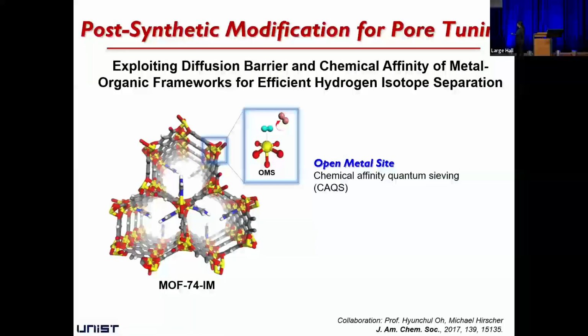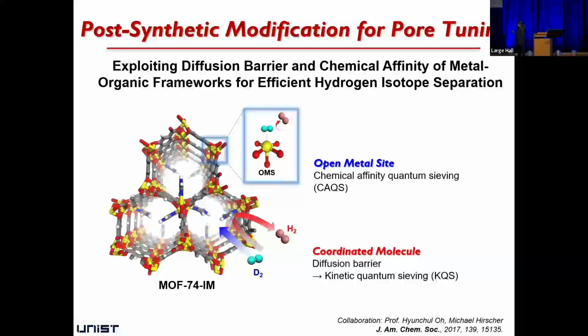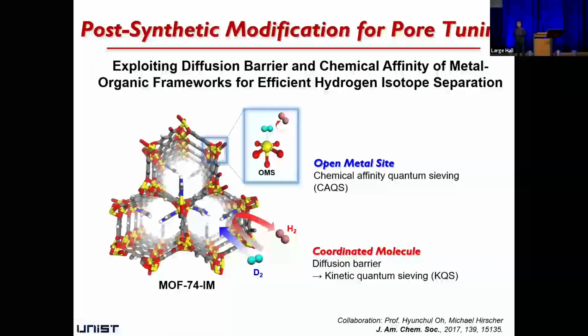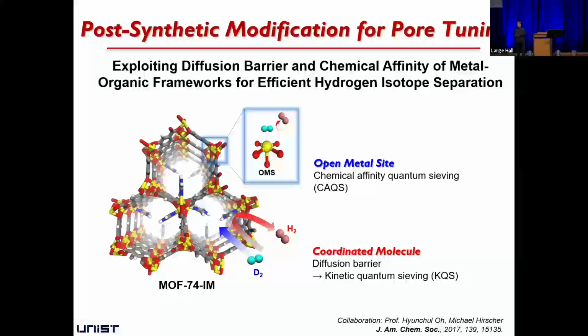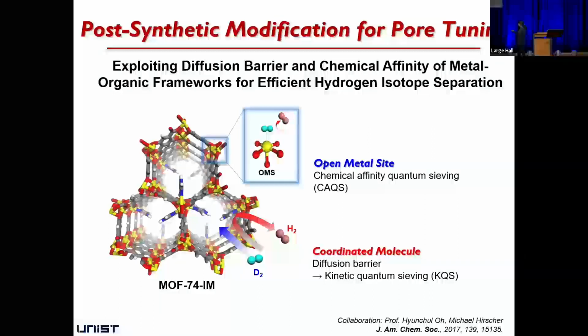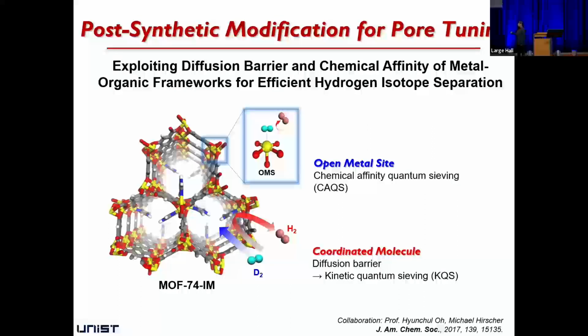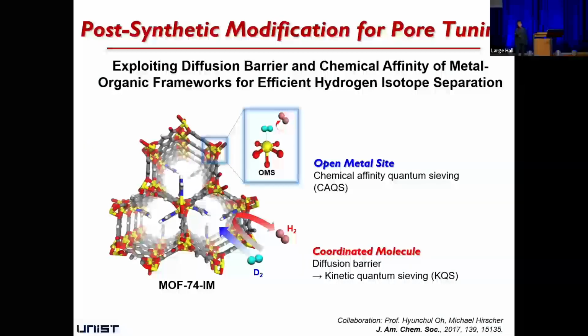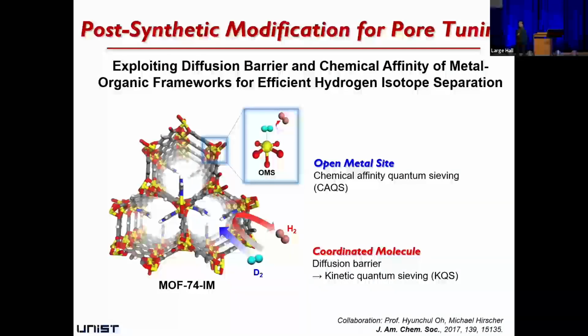So we choose the MOF-74. As you know, MOF-74 has a high density of open metal sites and very strong sites. So we can expect the chemical affinity quantum sieving effect from the open metal site, but MOF-74 has very large pores, so we cannot expect the kinetic quantum sieving effect. So then we decorate the pore wall with a small molecule, and this small molecule can act as a diffusion barrier. Then we can expect the kinetic quantum sieving effect.